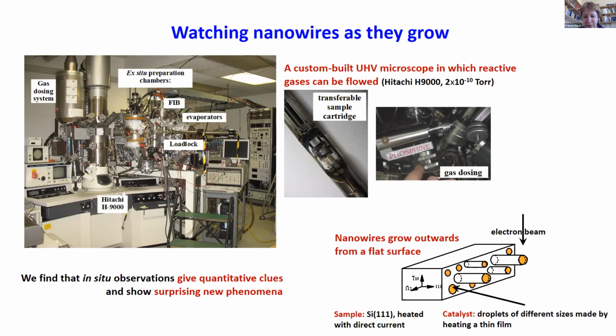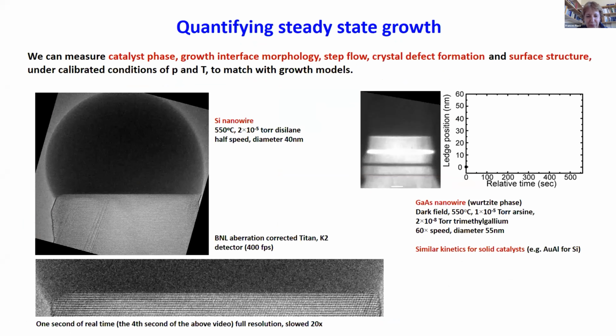So the kinds of samples that work well for nanowires are these vertical samples. The electron beam passes across the face of a little block of silicon. The front side is the polished side. You put the catalytic particles on the front side. When the nanowires go out sideways, they're in a perfect geometry for getting good images of their structure and their kinetics. So having set up this equipment, let's see what we get when we do the experiment. So we can measure the growth rate, the interface morphology, the phase of the catalyst, etc. during growth under calibrated conditions of pressure and temperature.